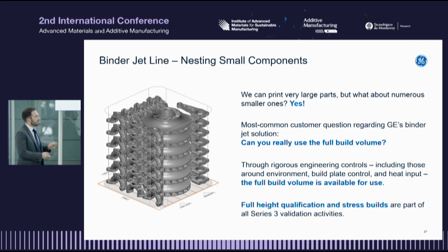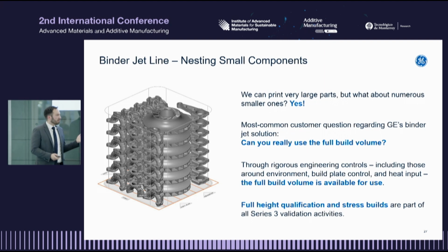The last thing we want to address in the handful of minutes we have is the most common question we get about binder jet: can I use the full build chamber? Simple answer, yep, sure can. This is pretty tricky when you think about how I can possibly, at full build in 316 stainless or any of the steels, move 650 kilograms, 100 microns at a time. And if I can't do that, if I'm at 125 microns of step, now my binder kinetics, my wicking, my temperature profile, all of those things are not as they were designed to be.